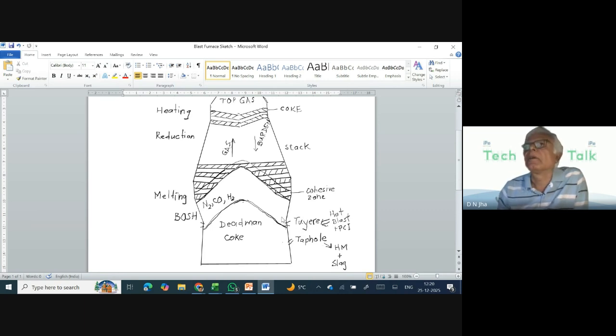Apart from that, we may have humidity, and that again gets broken here, C plus H2O, and therefore it generates CO as well as hydrogen. The PCI also has volatile material with direct hydrogen, so that hydrogen also accumulates here, and the hydrocarbons also break into CO and hydrogen. So we have only these three gases here in the Bosh: nitrogen, carbon monoxide, and hydrogen. Out of this, nitrogen is the inert gas because it doesn't react with anything else. However, carbon monoxide and hydrogen are the two gases which are very useful.